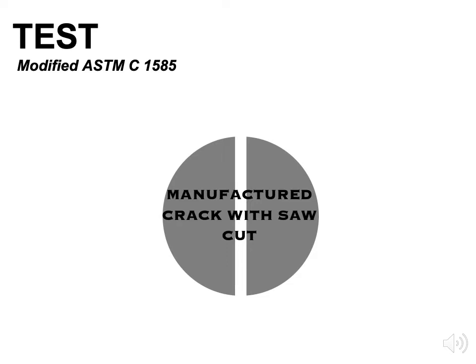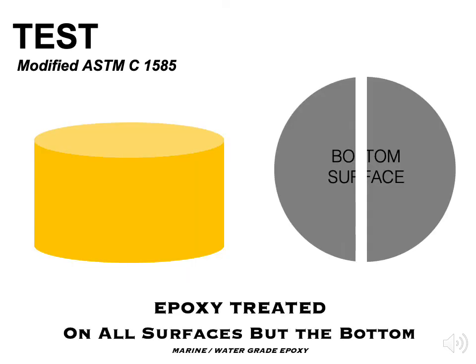Then what we're going to be doing is epoxying everything around that concrete sample minus the bottom surface. Now we're doing that for two reasons. One, to bring that crack together so we have a hairline crack, a 1/32 of an inch crack. And the other reason is per the ASTM C1585, where we want to just test that one bottom surface that's going to be touching the water, as you'll see here in a minute.